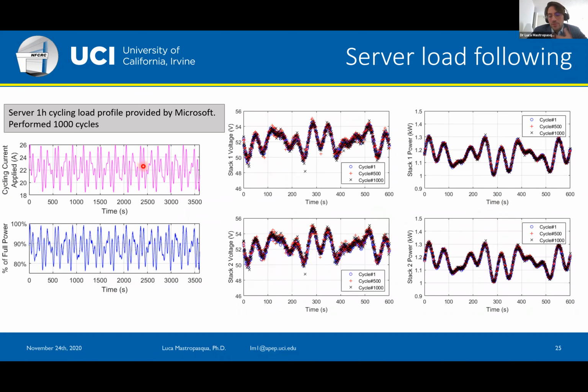So as I mentioned, we must make sure that these systems can operate dynamically. So we used a dynamic profile supplied by Microsoft and exercised the system for 1,000 cycles, each cycle 1 hour, and verified that the system could actually follow the load profile and then calculated the degradation, if any, of the two stacks. And actually, we couldn't measure any real degradation after 1,000 cycles. Between the first and the 1,000th cycle, the system was performing fairly well. So this was promising news for these systems to be exercised dynamically, such as in this case.